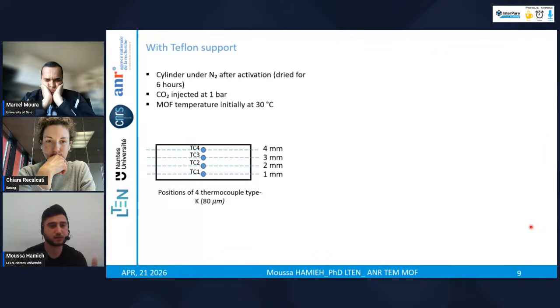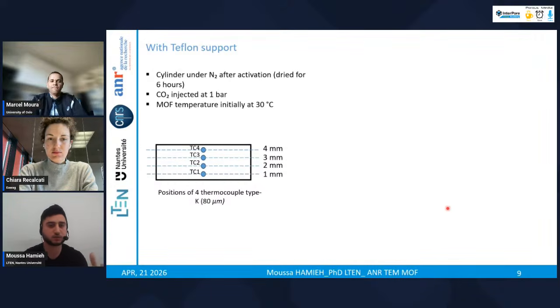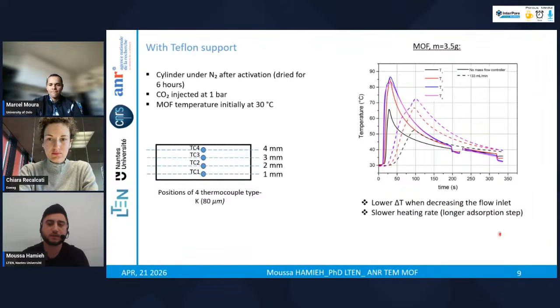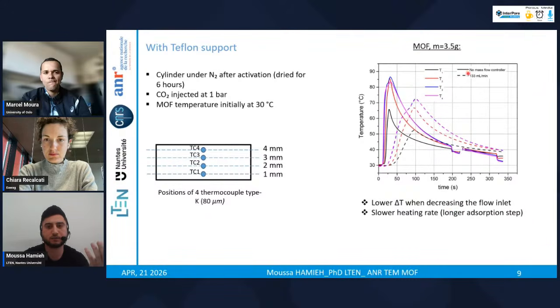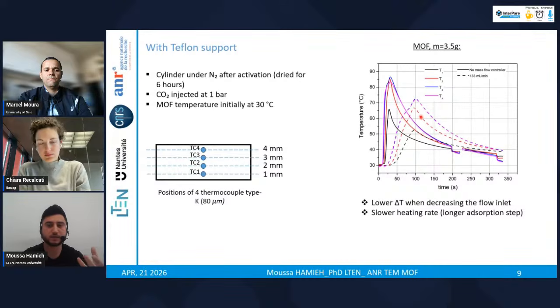Then after this activation, we wait until the MOF is cooled down to ambient or 30 degrees, and then we inject the CO2 at 1 bar. As first experiments, I injected directly from the bottle of the gas, so no mass flow controller. And then I also used a mass flow controller at 133 milliliters per minute. For the case of direct from the bottle, we see a huge increase from 30 to about 85 to 87 degrees. So we are talking about more than 55 degrees of delta temperature, which is not negligible at all. And when we add the mass flow controller, we see that the increase was lower, about 40 to 42 degrees. And it's also slower. It's not the same slope of increase in temperature.